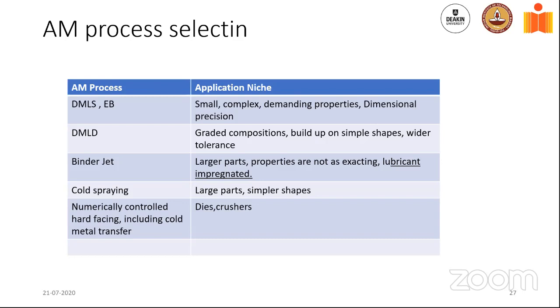We now have at IIT Deakin, for example, numerically controlled weld overlay machines. They've modified the weld overlay head so the bead itself is much finer in diameter, maybe around a millimeter or a millimeter and a half. The heat input is controlled much more carefully, so you have things like cold metal transfer going on. But the entire deposition head is put on a numerically controlled machine.